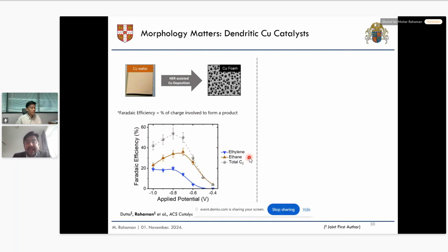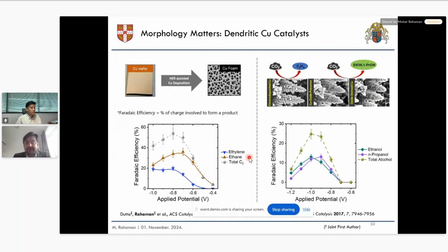Now, how about alcohol? Can we get alcohols also from copper? The answer is yes, but we need to activate the copper dendritic material. You can see here the as-prepared copper dendrite. We can see a honeycomb structure here. Then we have to oxidize the copper dendrite to copper oxide, and then electrochemically reduce the copper oxide to get nice nanostructured copper on the dendrite surface. If we get this, then we can shift the selectivity of the carbon dioxide conversion process from ethylene to multi-carbon alcohol.